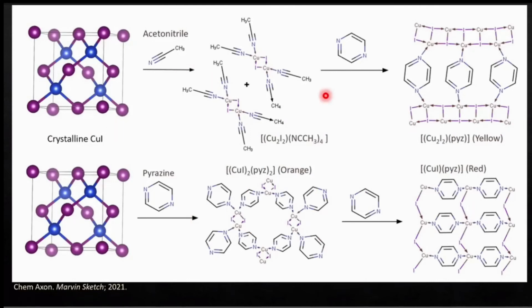So looking at that in a general reaction mechanism, we have crystalline copper iodide here. The acetonitrile diffuses through that crystalline lattice, breaks it into mobile dimers, and then the mobile dimers are assembled when the pyrazine is added into this yellow polymorph. While in the case of the pyrazine diffusion, if the pyrazine diffuses through the crystal lattice, then it's going to break up the crystal lattice into these isolated dimers surrounded by pyrazine, which forms the orange polymorph. But then this is kind of unstable because it has these very large pores, it's two-dimensional, and it just generally is not very stable. It's easy to crush those pores. And so it will spontaneously decay into the more thermodynamically stable red polymorph over here.